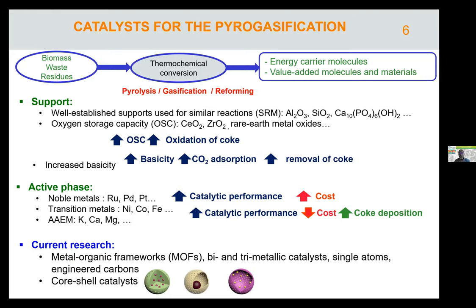And also the support brings the basicity. The basicity increases the CO2 adsorption that helps to remove the coke that is deposited. And the active phase is mostly made of metal, noble metal, which is interesting because they do have a very good performance in transformation, but they are costly.